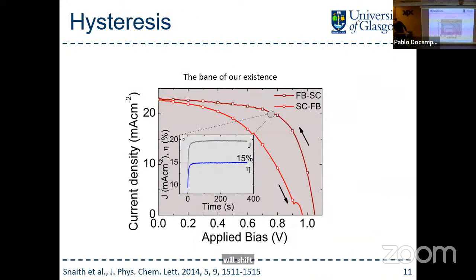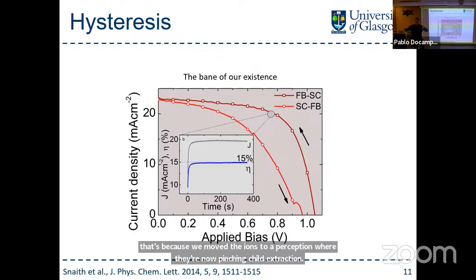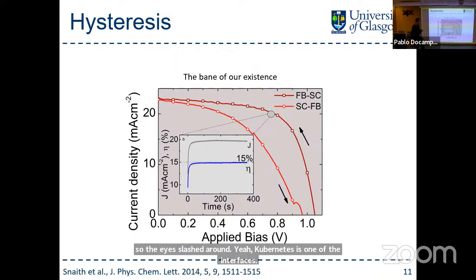Now, the obvious outcome of this, if you're not familiar with J-V curves for solar cells: for a solar cell to be good, you need to have a square-looking curve. The less of a square it looks like, the worse it is. This is the same cell, just scanning one way and coming back. It's a hysteresis loop. You can see that one of them is a lot worse than the other one. That's because you've moved the ions to a position where they're now hindering charge extraction. The ions sloshed around are accumulating at one of the interfaces, and they catalyze recombination, so you lose charge. This is why you observe that loss.